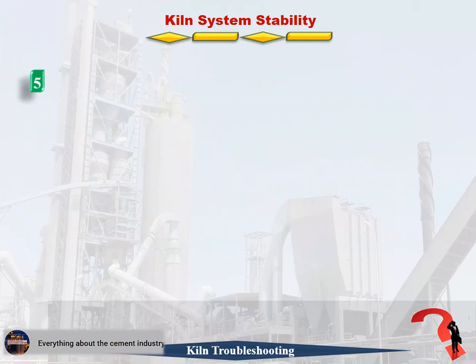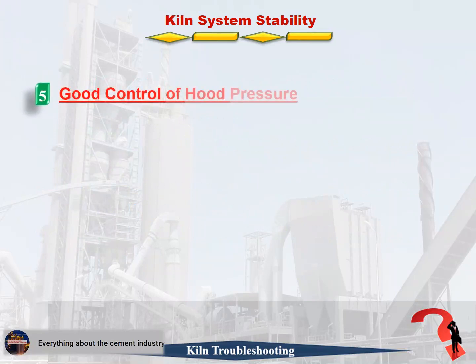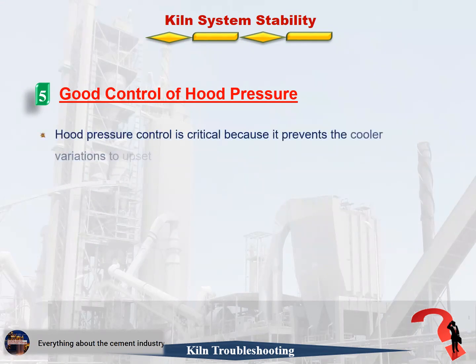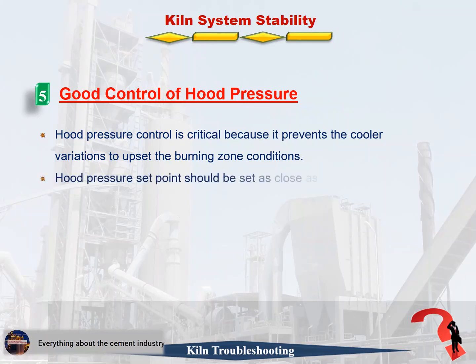5. Good control of hood pressure. Firstly, hood pressure control is critical, because it prevents the cooler variations from upsetting the burning zone conditions. Secondly, hood pressure set point should be set as close as possible to zero, while remaining negative.